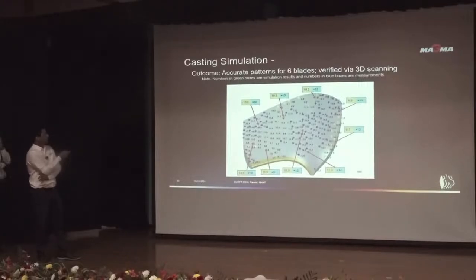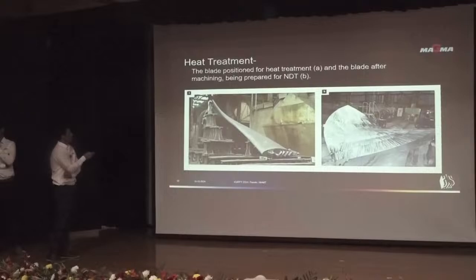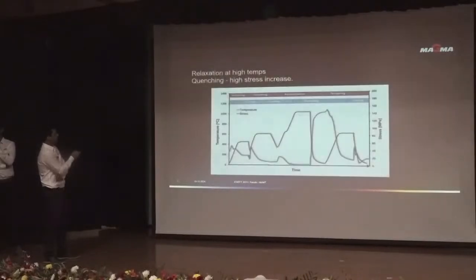So what was the outcome of this? We made accurate patterns of 6 blades, did 3D scanning, and found these results. The green color shows the simulation results, and the blue shows the actual measurements. This is how the blades were positioned for heat treatment and after machining, preparing for NDT.